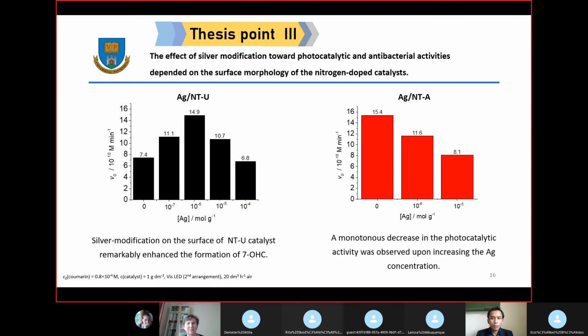The third thesis point is the effect of the silver modification on the photocatalytic activity and the antibacterial activity depending on the surface morphology. We modified both catalysts with silver nanoparticles, and for the NT-U catalyst, the photoactivity could be improved by silver modification until the optimum concentration. But in contrast, for the NTA catalyst, the silver modification was not favorable for the photocatalytic activity. It may be due to the different morphology of the catalysts.